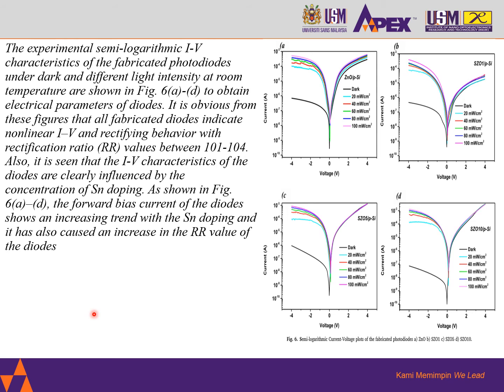The experimental semi-logarithmic I-V characteristics of the fabricated photodiodes under dark and different light intensities at room temperature are shown in Figure 6a to d to obtain electrical parameters of the diodes. It is obvious from these figures that all fabricated diodes indicate nonlinear I-V and rectifying behavior with rectification ratio values between 10^1 and 10^4.